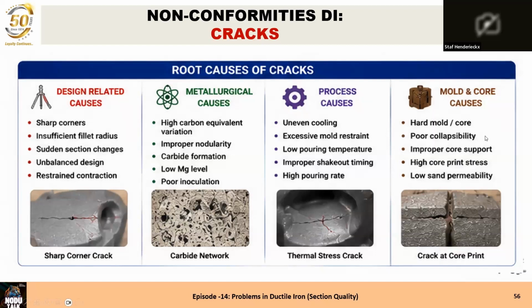You need the difference in temperature. Excessive mold restraint, which you have mainly with chemically bonded sand, that sometimes it's impossible for the metal to shrink, and then there will be a crack. Low pouring temperature, that I shouldn't call a crack, but it can be, let's say, a cold crack, in the sense that two metal streams that touch each other and there are some oxides in between, they will not connect properly. So it looks like a crack, but it's a different cause due to the low temperature.